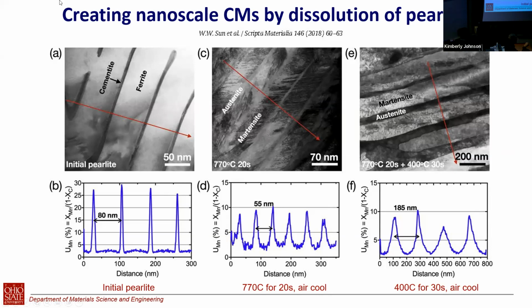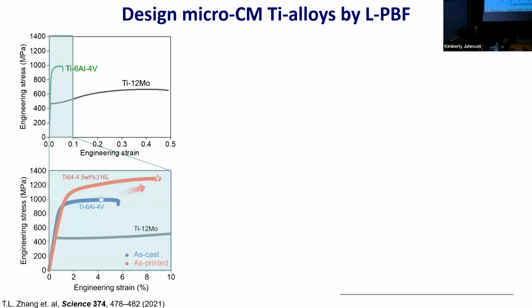And then when they do the cooling again after the up quench, they form this alternating layer of austenite, martensite, austenite, martensite. And then when you apply a load, the martensite simply grows and eats up the austenite, which gives you very extended work hardening, or this TRIP effect, the transformation-induced plasticity effect. All right, so that's very good.